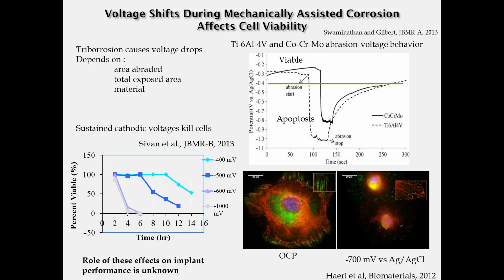So firstly, we've been studying since the late 90s, early 2000s, the idea that when you apply a cathodic voltage, when you drive reduction reactions, you can kill cells on surfaces rapidly. So when the surface becomes minus 600 millivolts, you can see cell death on cells grown on that surface in as short as about 2 to 4 hours. The more negative that potential, the faster that reaction takes place.